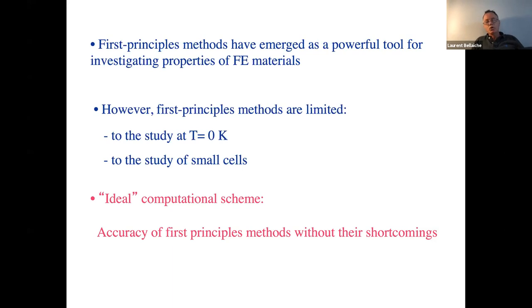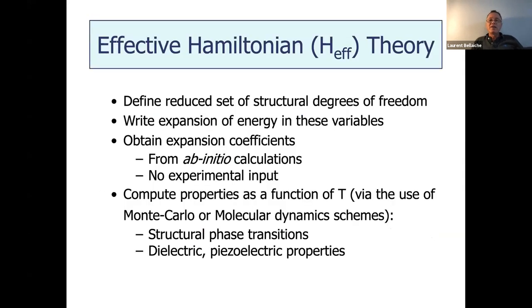But if you want to mimic complexity, especially for nanostructures or solid solutions, you really need to go to, I don't know, 10,000, 100,000, 1 million atoms. So an ideal computational scheme will be as follows. You keep the good things about first principle methods, the accuracy, but you get rid of these two shortcomings. So that's the basic idea behind effective Hamiltonian.